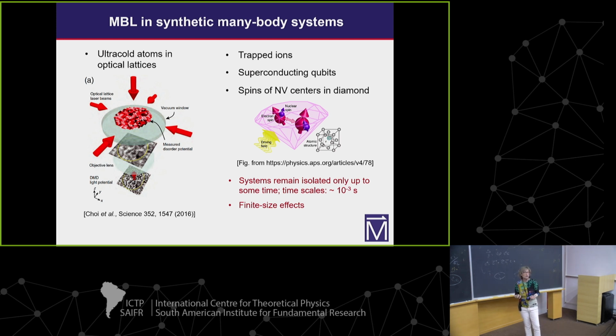The other problem with all of these experiments is that the interpretation of many of them has been complicated by finite size effects — these are not very large systems. The largest one, maybe, done for the fermionic lattice, had a few thousand atoms. Similarly, many numerical simulations are also plagued by finite size effects. So in order to really make comparisons to theory, it would be nice to have experimental systems much closer to the thermodynamic limit.